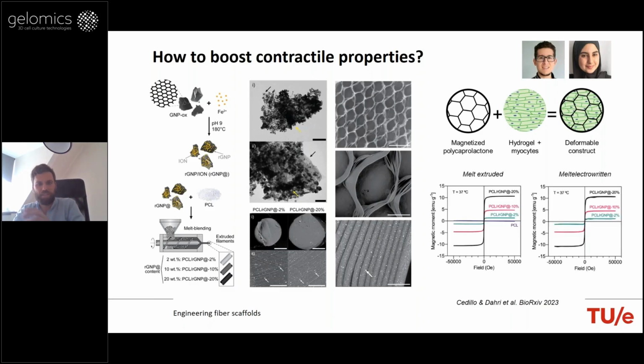Of course, the next question was to understand what the magnetic properties of these materials were. So we compared constructs loaded with different percentages of particles from 2% up to 20%. When we look at the magnetic hysteresis curves on the right side of the plot, we showed that when we compare the melt blended filaments and the melt written filaments, there was no decrease in the magnetic moments. And all the constructs show, for those familiar with the field, a typical ferromagnetic behavior, as characterized by these hysteresis curves. So the melt writing process was not detrimentally affecting the magnetic properties of our materials.